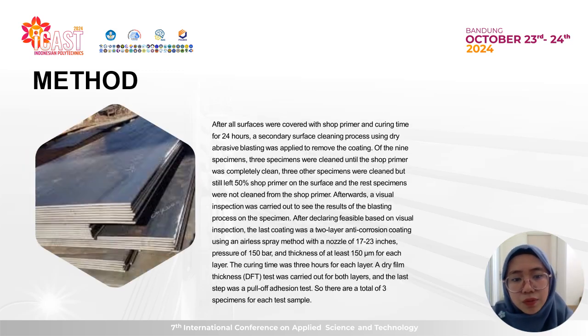After all surfaces were covered with shop primer and cured for 24 hours, a secondary surface cleaning process using dry abrasive blasting was applied to remove the coating. Of the 9 specimens, 3 specimens were cleaned until the shop primer was completely clean, 3 other specimens were cleaned but still left 50-100% shop primer on the surface, and the last specimens were not cleaned from the shop primer. Afterwards, a visual inspection was carried out to see the result of the blasting process on the specimens.